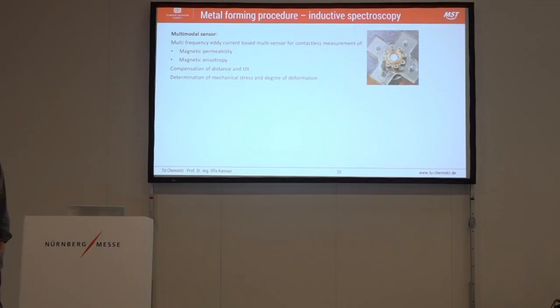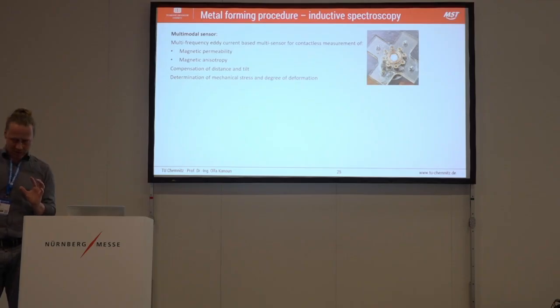It's the so-called MST flower. MST is our shortcut, and the flower is the main coil and some surrounding coils. With this, we can measure anisotropies, and I want to highlight the permeability of the material. Now we need to ask ourselves which phenomena cause a change in the permeability, like stress, torque, grain size, temperature. All these parameters cause a change of permeability, and we can measure it without touching or destroying the material, because of our multispectral approach.